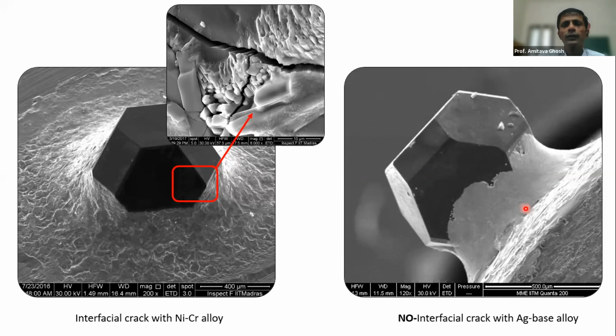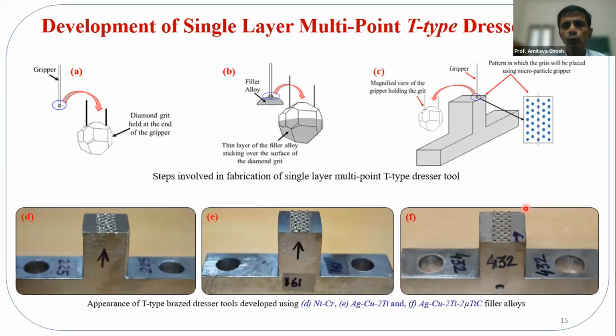The grit will not get broken, but the alloy will be worn out, and the grit will be prematurely pulled out from the matrix. That we didn't want, so we wanted to enhance the wear resistance characteristics of this alloy, and we just added some ceramic reinforcement, and we did it. So this is all about joining.